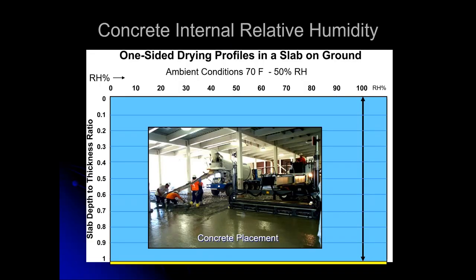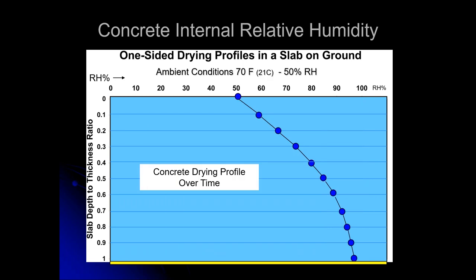For example, and this is assuming now that the ground is taken out of play, that there is an effective low permeance vapor retarder directly underneath the concrete or we're on metal decking. When the concrete hit that base, be it the vapor retarder, the ground, or the metal decking, it's soaking wet. It's 100% relative humidity top to bottom. Now, our ambient conditions are 70 degrees Fahrenheit, 50% relative humidity. And over the course of the weeks and months that follow, moisture will evaporate from the surface of the slab, and ultimately the relative humidity in the very top of the slab will equilibrate with whatever the relative humidity is in the ambient environment. So in this case, it's 50%.